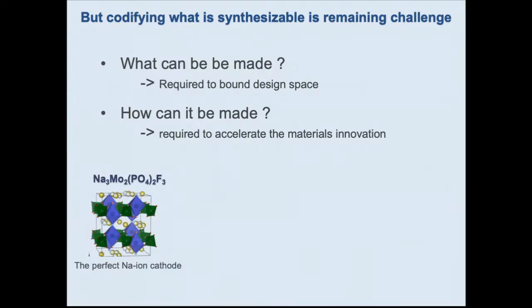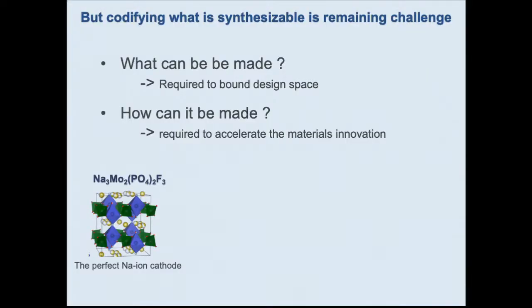This is really driven by a need, right? We have designed several compounds that look nothing special, but we can never make them. And they would have tremendous applications. So sodium molybdenum fluorophosphate, this is a known crystal structure. It's known for vanadium. This is actually calculated to be a ground state. I have spent, well, my postdoc and student have spent 6 months in the lab with all kinds of synthesis techniques and no sign of life whatsoever. And after 6 months, people give up, right? Because it's sort of a true non-result that is even hard to publish.